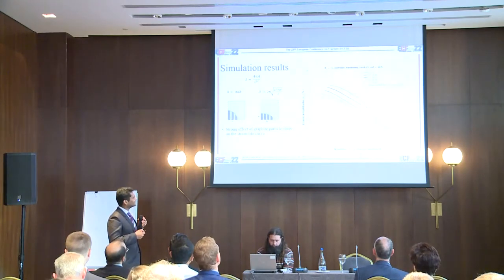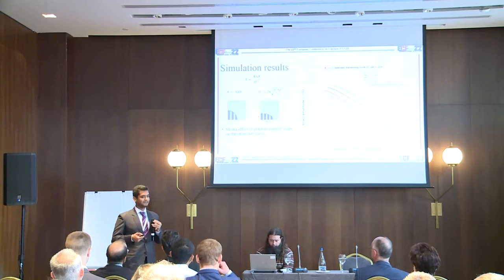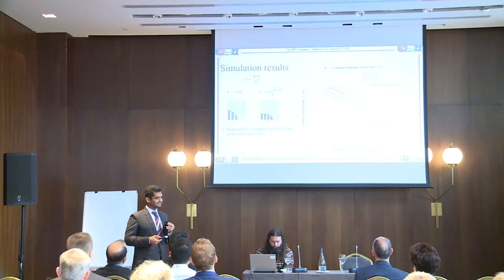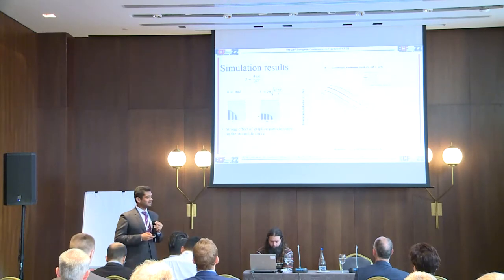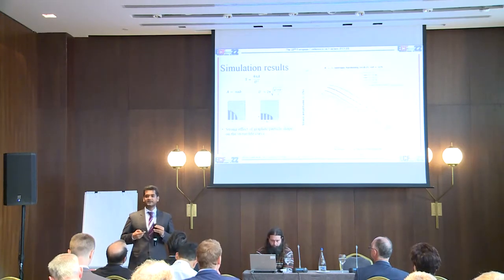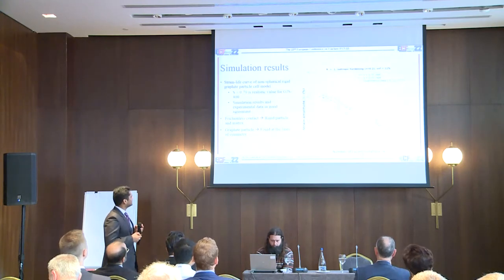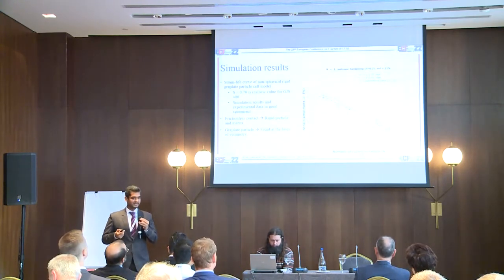Looking at the results of the shape simulation: when S equals one, it is a perfect sphere. As we decrease the shape factor — meaning we model an elliptical graphite particle — the fatigue lifetime decreases, and we obtain more realistic values of fatigue life. From the experimental literature review, we found that the shape value S equals 0.70 is quite realistic for GJS-400. So S equals 0.7 can be defined for the ENGJS material.